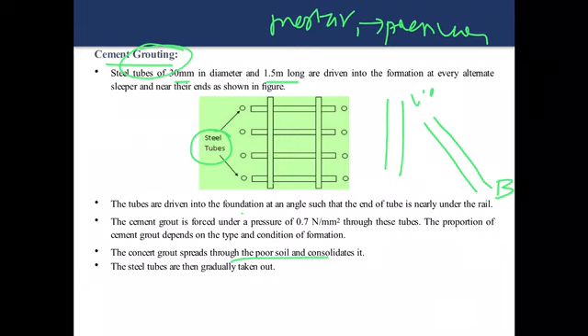Now once the steel tube is inserted, within the steel tube, we have to push the mortar under the pressure. The mortar will be forced into the steel tube under the pressure. The pressure maintained will be the 0.7 Newton per mm square. Once the cement get hardened, the steel tube will be taken out. Now with the help, the cement grout will be within the soil and that will improve the strength of the soil.